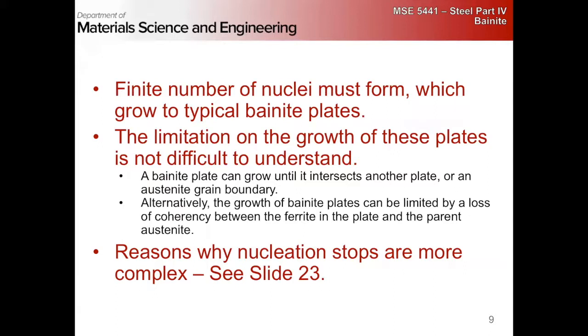The limitation of growth, we can understand that. If we nucleate a plate and then it grows, it can either grow until it intersects another plate or hits a grain boundary, or because I said that there's a large shear that needs to be accommodated, it leads to plastic deformation. That plastic deformation can lead to the interface becoming decoherent, and then you're not able to continue growth.